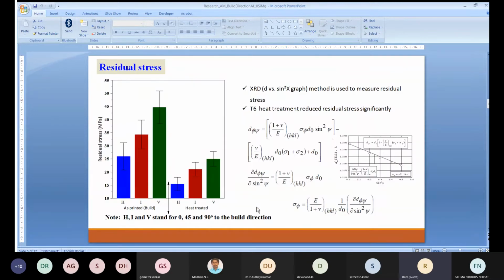First thing we measured in the as-built condition and heat-treated condition. We have considered two cases: just print it and test it. Another one is subjecting them to T6 heat treatment, that is, heating to 540 degrees Celsius for solution treatment, followed by quenching and aging at 160 degrees Celsius. So that is called heat treatment.